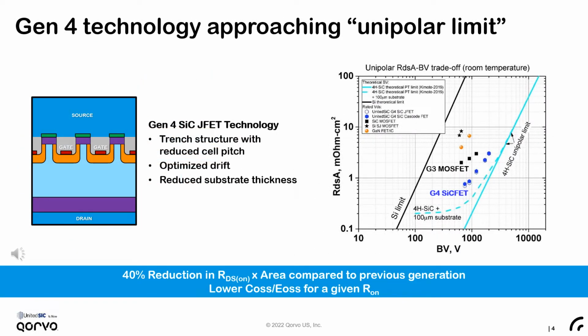The Gen 4 products center around our new vertical trench JFET technology that's the closest to the unipolar limit of silicon carbide. We've introduced a new trench structure with reduced cell pitch and an optimized drift layer. To go along with these device cell improvements, we've also employed a further reduced substrate thickness to arrive at the industry's best specific on resistance. The new Gen 4 1200 volt FETs are nearly half the specific on resistance of competing technologies and are 40% lower than our previous generation. These performance improvements yield a lower output capacitance and lower stored energy in that output capacitance for a given on resistance.